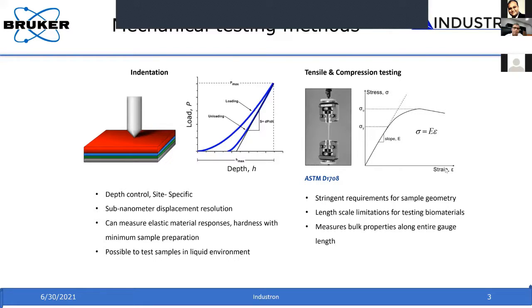Okay. So with that, my next slide shows the idea of what indentation means. This is for people who are even new to this field. What we do in nanoindentation is you take a very sharp probe made of diamond, and you apply a load through the probe onto the sample surface, and you penetrate the sample surface. You load and unload, and you create an indentation on the sample surface.